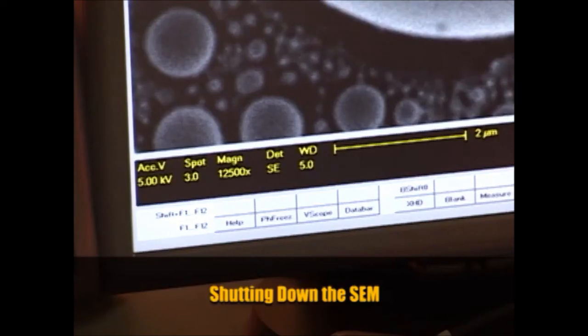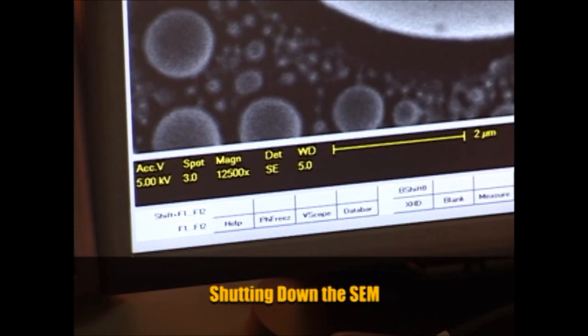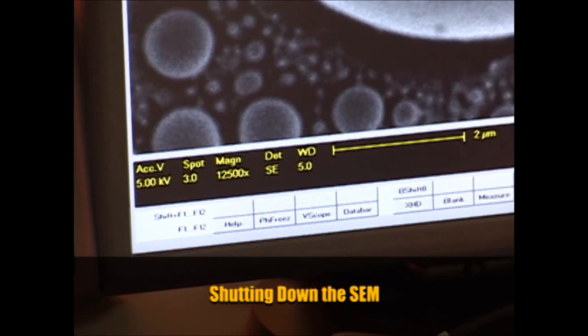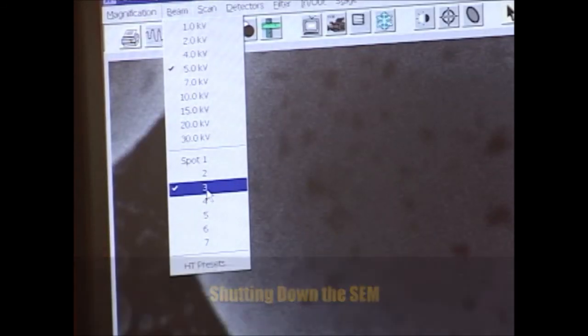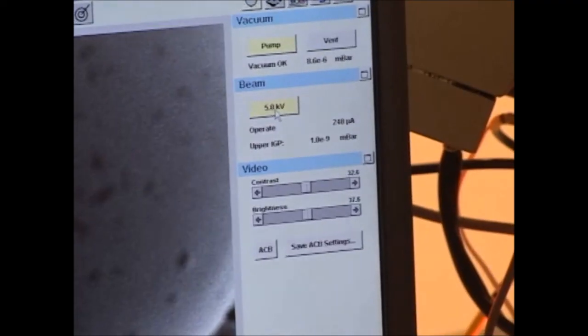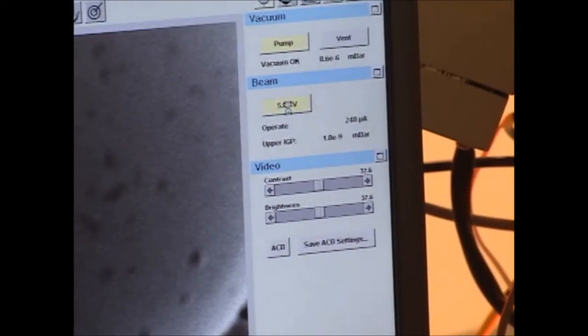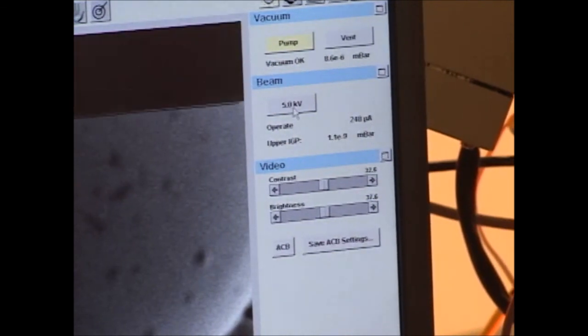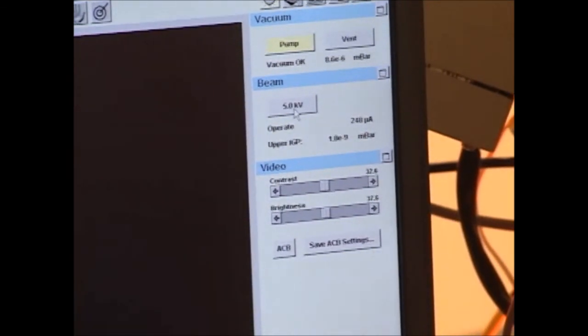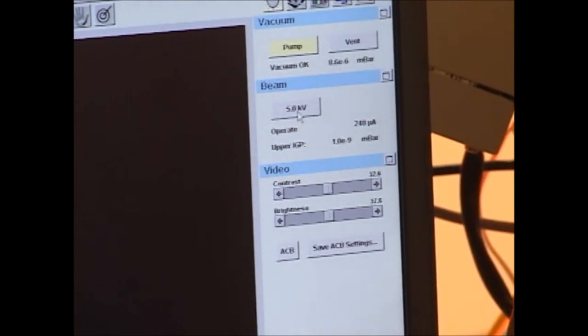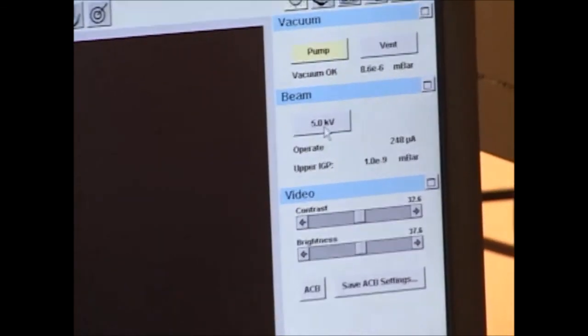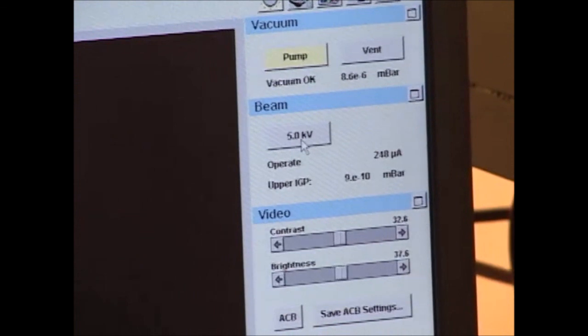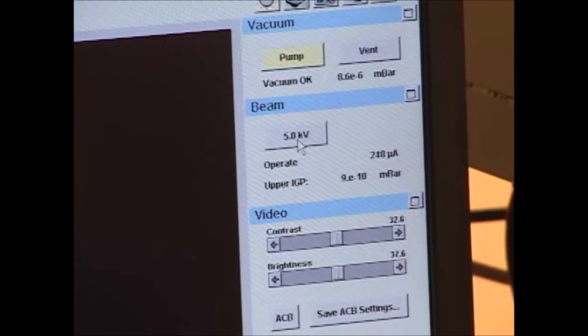We like to keep the microscope set at 5 kV, spot size 3, when it's not in use. So if we had changed the accelerating voltage or the spot size before we shut down, we would set them back to these default values, 5 and 3. And then you turn the beam off by, again, clicking the 5 kV button in the beam submenu. And you'll hear the column valve close. That means that the sample chamber is sealed off from the column, and we can vent it to atmospheric pressure.